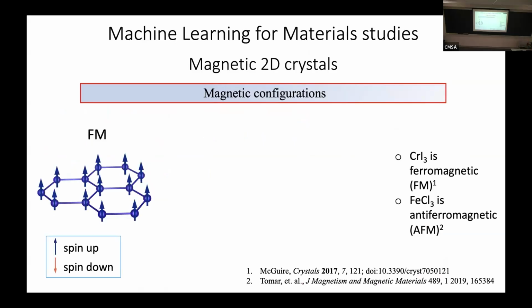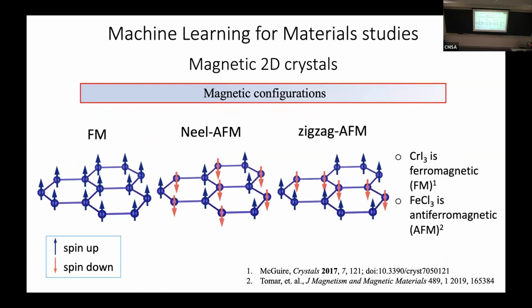We considered ferromagnetic ordering and anti-ferromagnetic ordering of the materials. For instance, we already found that chromium triiodide is a ferromagnet. Turns out iron trichloride, just by changing the chemical composition of the material, becomes an anti-ferromagnet. I think that's pretty remarkable. It's hard to predict just by looking at the chemical composition what the magnetic properties will be. At least I can't do it. So we can calculate using DFT, but if you want to really predict 10,000 of these candidates, you need something else to do it, something like AI.